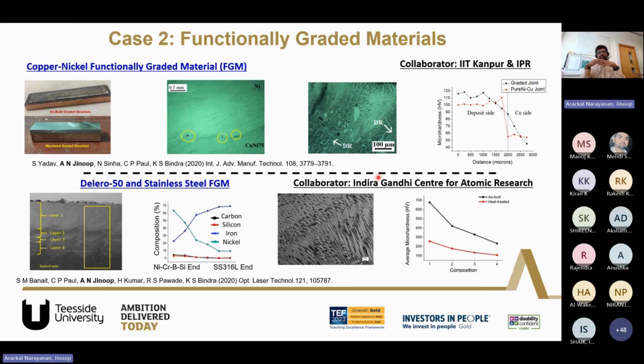In this, what we did is we mixed the powders in advance, and then generated the structures by gradually changing the composition from one end to the other end. So the composition was 0% stainless steel at one end, the other side was 100% Delero-50. So we could get gradual change in composition, as you can see in this diagram. The gradual change was observed, and the gradual change in mechanical properties were also observed in this case.